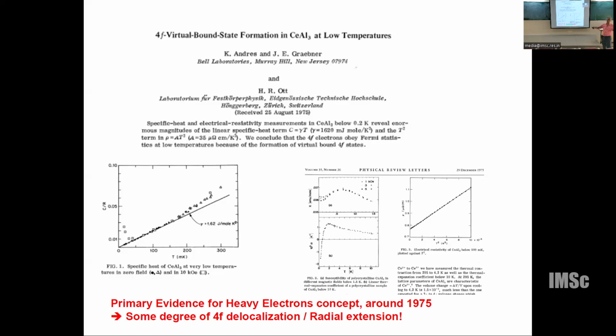High temperature is like magnetic. So you could find here that in this compound, the gamma value is 1.62 joule. It is more than 3 orders of magnitude larger than what you expect for a simple metal. This is a complete transformation of our knowledge.